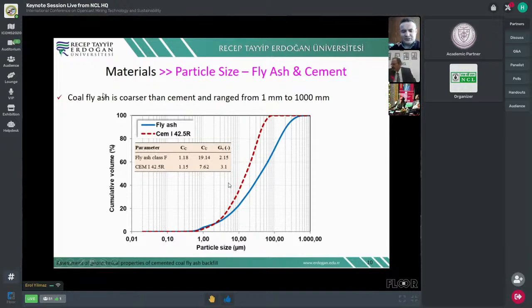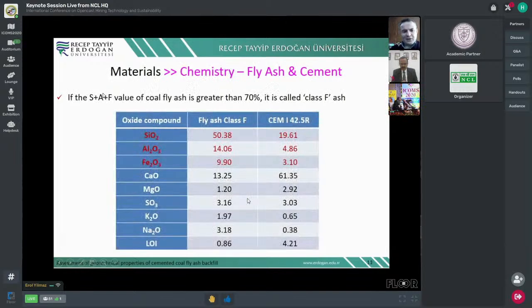and ranges from 1 micron to 1000 microns, as you can see, and cement is finer than fly ash. There are also some coefficient of curvature and uniformity values, as you can see in the small table, and the specific gravity of fly ash is 2.15, while the specific gravity of cement is 3.1. Here also the chemistry of fly ash and cement.